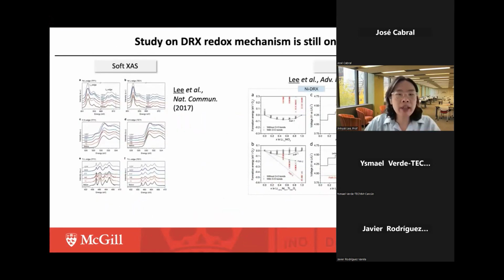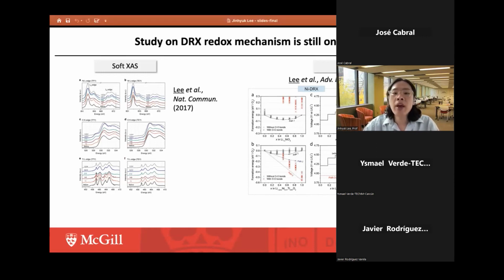I would like to say that the one I described is a purely theoretical study, but in fact, we are continuously studying this combined redox mechanism using both soft X-ray absorption spectroscopy and hard X-ray absorption spectroscopy, because they can actually analyze the real electronic structure of this cathode material during charging and discharging. So we can understand this experimentally, and also use density functional theory to further investigate.